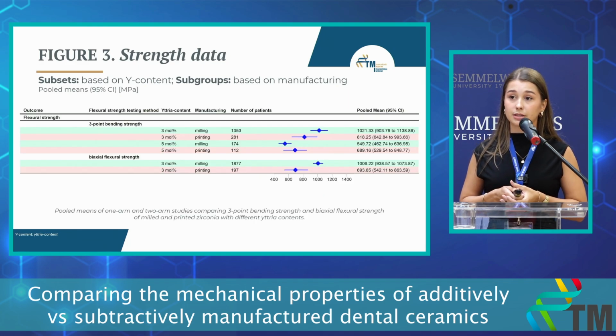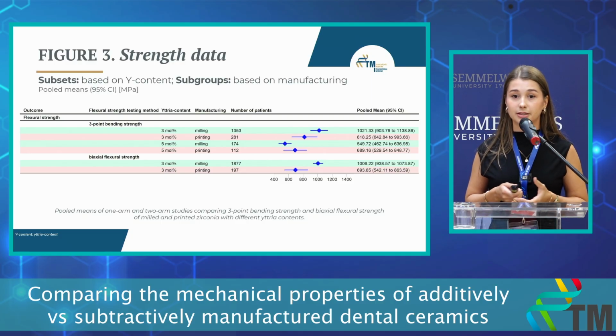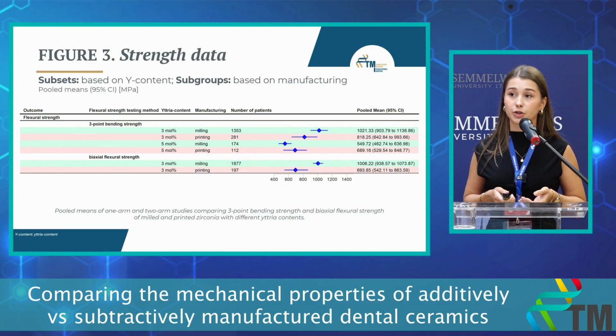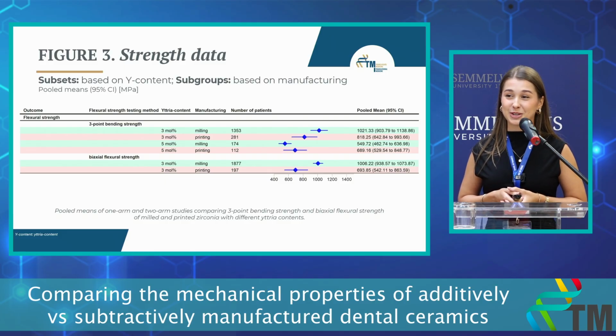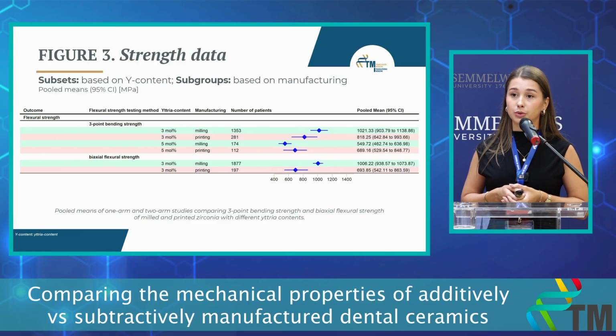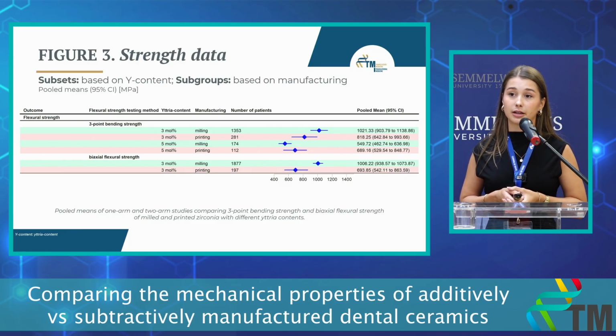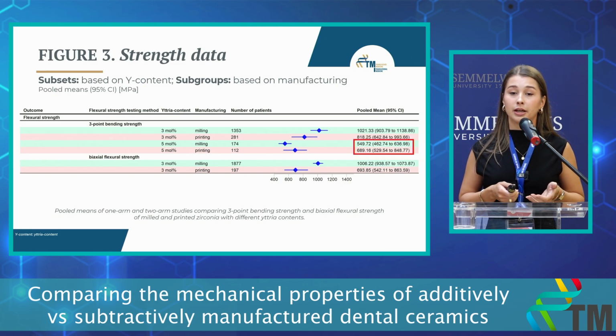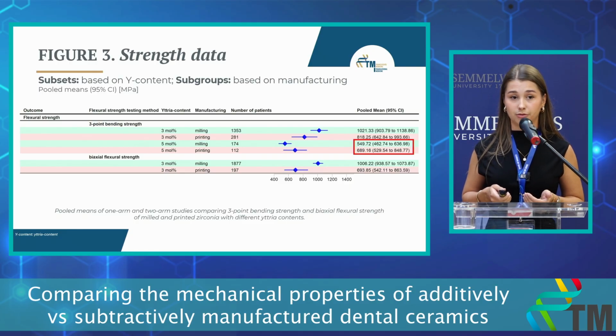You can see the results on this summary plot, and if we look at the 3-point bending strength, we can see this mentioned pattern, which is already well known in literature. So increasing the yttria content of zirconia decreases flexural strength, also giving us significant results if we look at the biaxial flexural strength data. But what I would like to show you is if we look at the 5 mole percent yttria stabilized zirconia, it has higher strength values than the same zirconia produced with milling, which emphasizes that with printed 5 mole percent yttria stabilized zirconia, we could get really good aesthetical results without compromising for much lower flexural strength. And it also emphasized that maybe the strength of printed zirconia is not as much influenced by the yttria content.